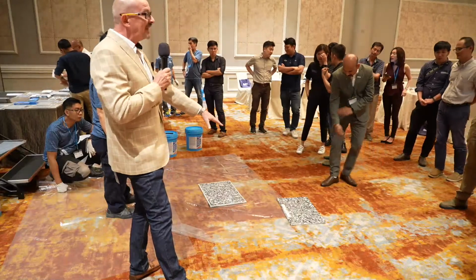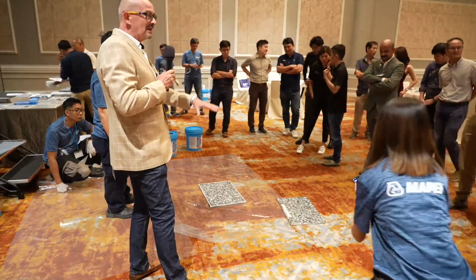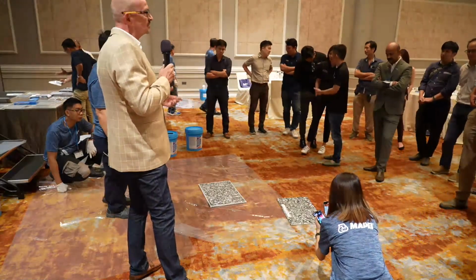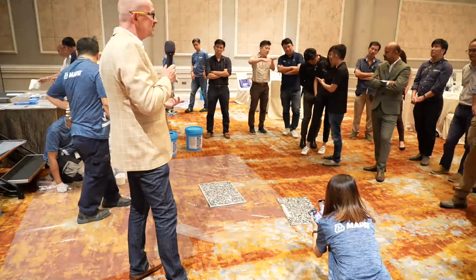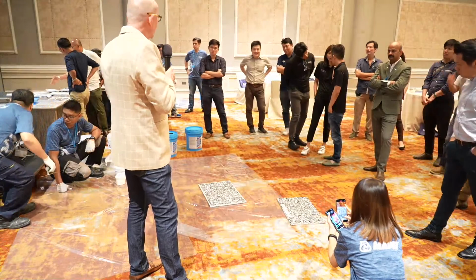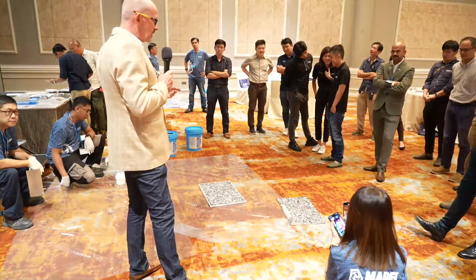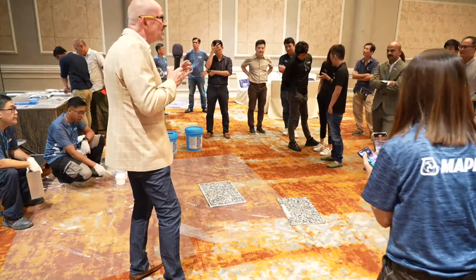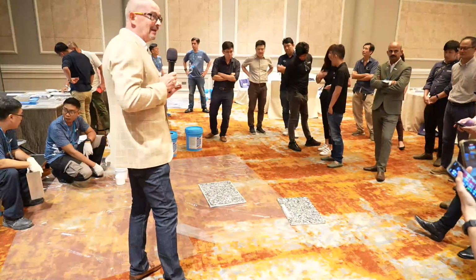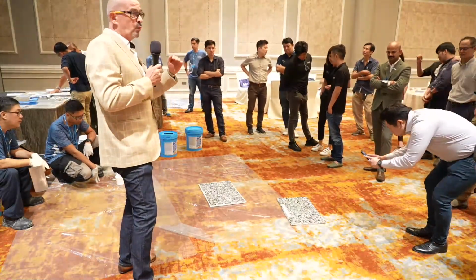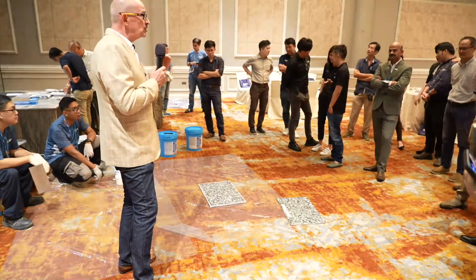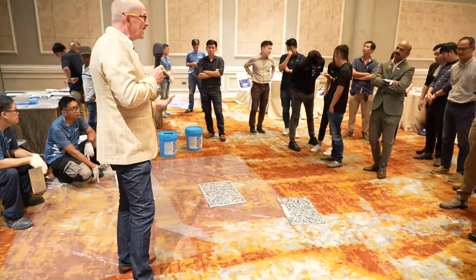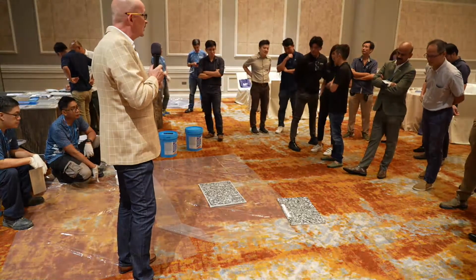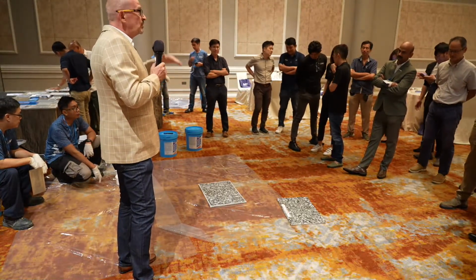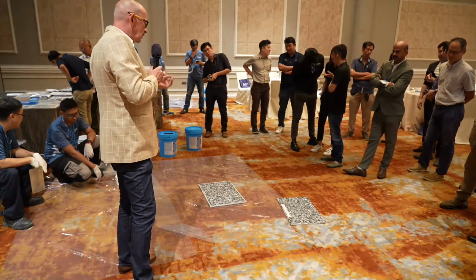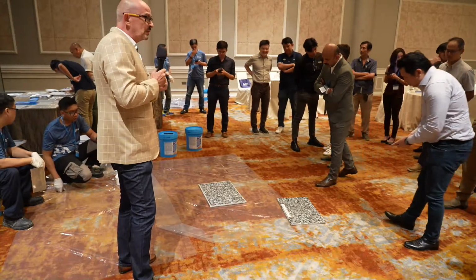The good part is that you use these flakes and this combination of white and black, blue and white, so you can't see the scratches so much. We have applied this in our office, in our warehouse area, with people running over it every day, right? And the scratch resistance, the hiding power, the camouflage of cracks is very good, very high. So again, we can also have a higher quality application or a lower quality, depending on your budget. This is higher quality, meaning we have primers and a good base coat of 312, a durable solid material. We then apply the flakes, do a sealer with 300 TRP and roll over again with 300 TRP. High durable, low yellowing material.